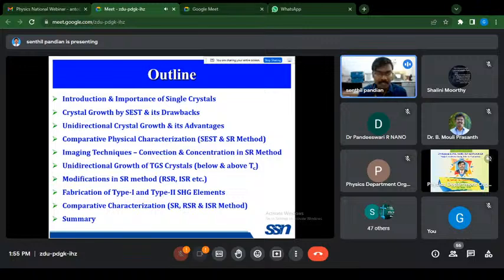For the curiosity to grow these TGS crystals, we have also tried to grow the crystals in the ferroelectric phase and also the paraelectric phase. We compared the physical properties and the crystalline perfection, and we concluded how the phase transition is used for the practical IR detector application. And we have modified several things in the SR method, and we have rotated the complete experimental setup. It is the RSR method, and we have also tried to avoid the impurity segregation in this SR method.